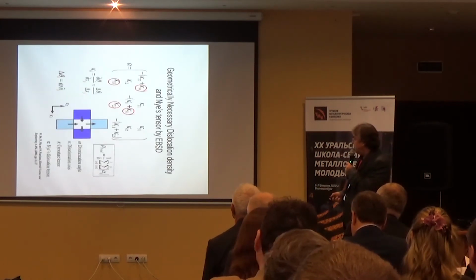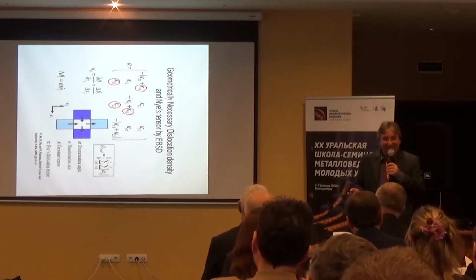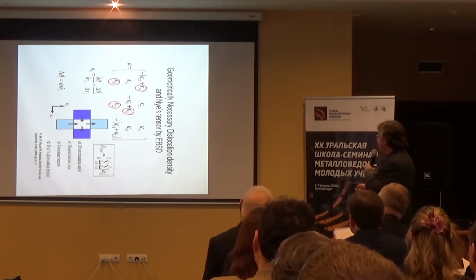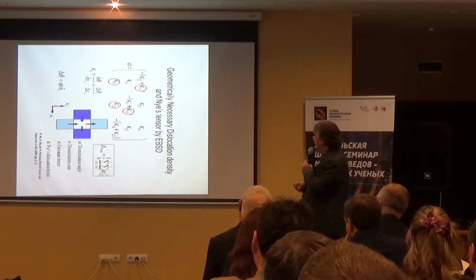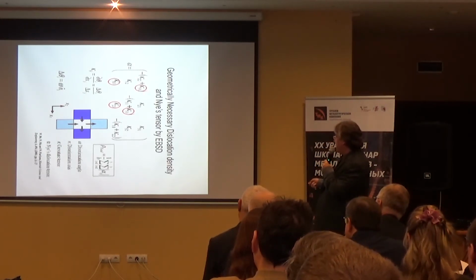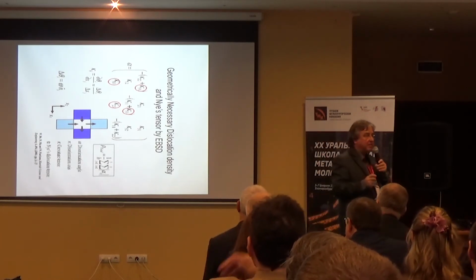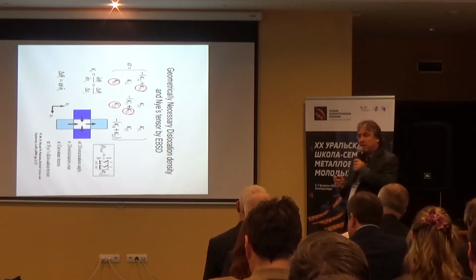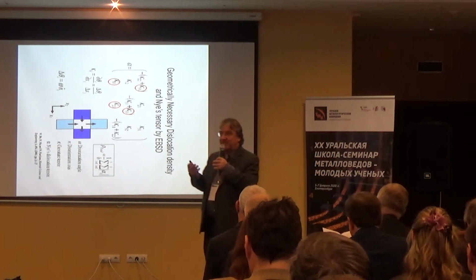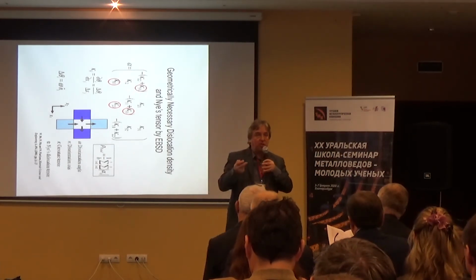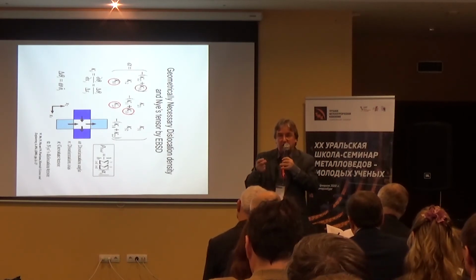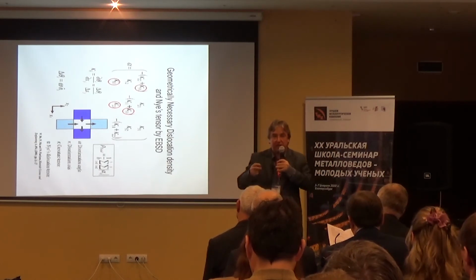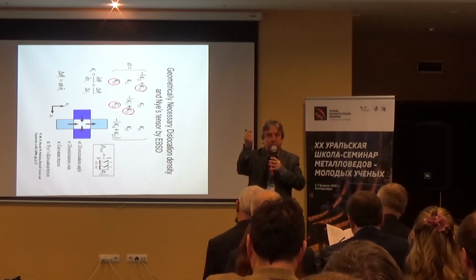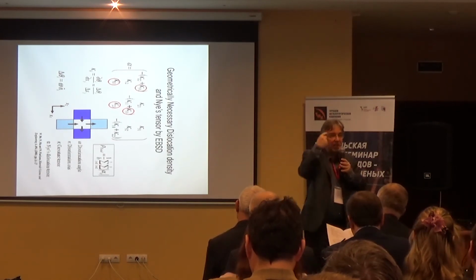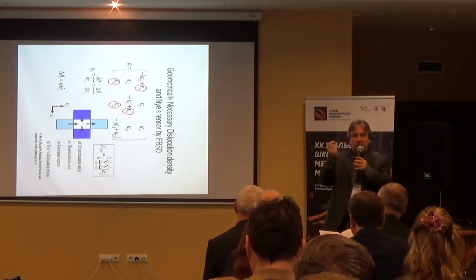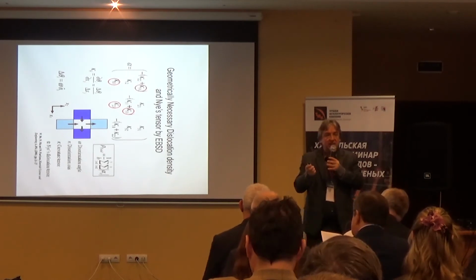Oh, this is a mistake. If you turn your head to the right, what is written here is the Nye tensor, which gives you the relation between the crystallographic curvature and the density of geometrically necessary dislocations. Geometrically necessary dislocations are statistically the dislocations that give you a non-zero closure vector of the Burgers circuit. So if you have a group of dislocations, you sum all of their Burgers vectors, the total sum, or the total integral, so to say, that remains over is the closure vector of the geometrically necessary dislocations.